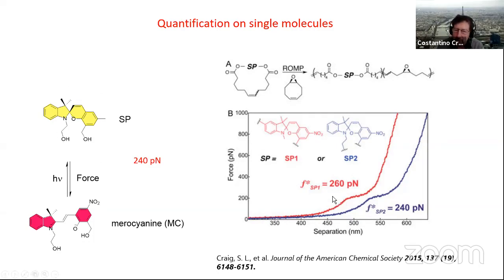So if you look at these curves here, there's a force versus separation. This is in nanometers. He's pulling on these daisy chain molecules of spiropyran. And at a given force, around 250 piconewtons, you have an opening of this cycle. This is about a tenth of the force to break a carbon-carbon bond. So in this case, at that level of force, you change the color. If you can be that quantitative, it may be possible to use this molecule also in materials, which is our idea, to be quantitative with force.